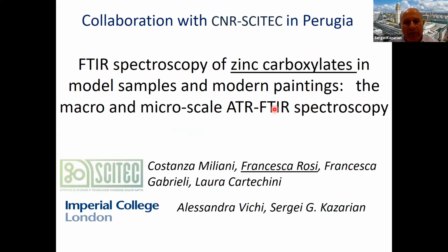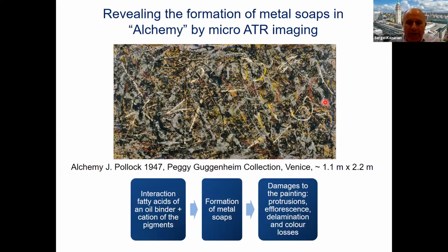But here, I would like to show you our results in collaboration with their group. What we wanted to study by ATR-FTIR micro-imaging was how fatty acids interact with the binder and form metal soaps. As you know, oil can interact with some metal oxides in a saponification reaction. But importantly, it would be a very destructive formation of soaps, of carboxylates, disruptive for the painting.